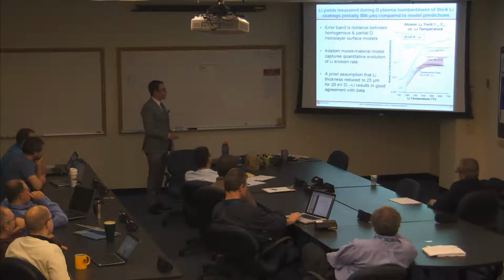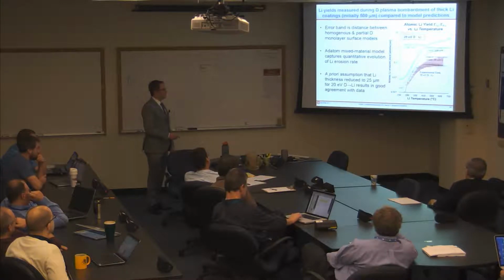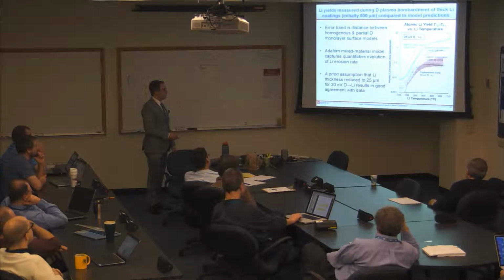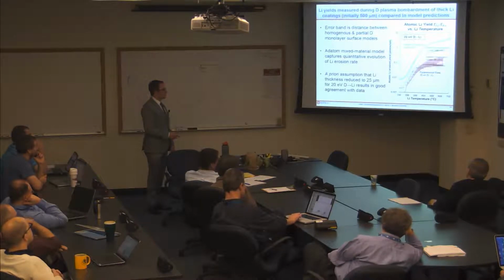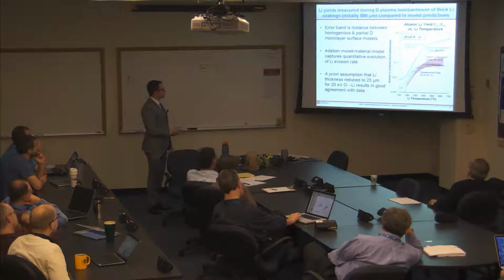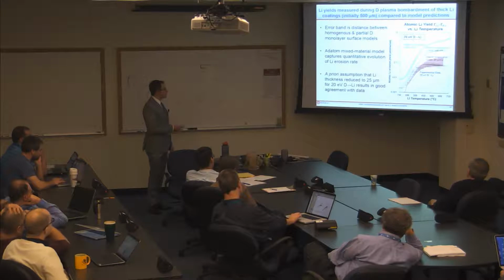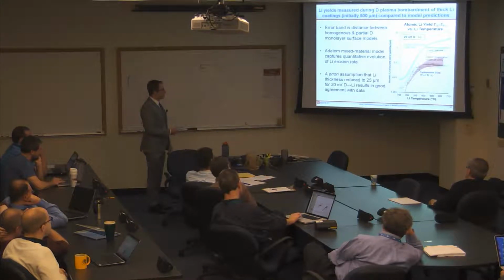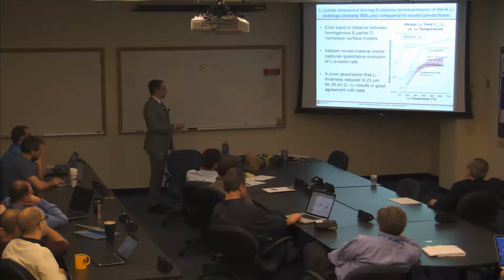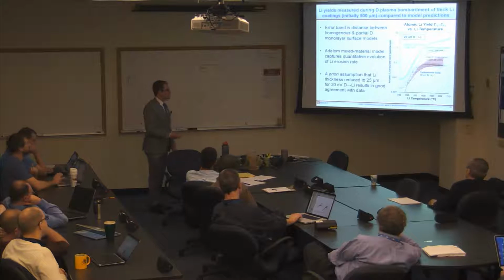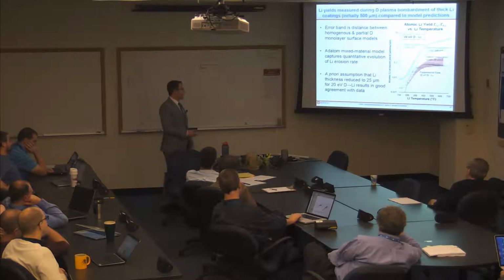And so I've plotted the predictions of the atom evaporation model for the beta equals 0 case, so no deuterium implantation. 500 microns, which would have been the initial thickness, and then 25 microns, which seems to fit the data in terms of what the reduction in the thickness seemed to be. And the experimental data is given in black here. So you get good agreement quantitatively between the atom evaporation mixed material model and the data with the a priori assumption that the thickness is reduced to some smaller value from 500 microns.